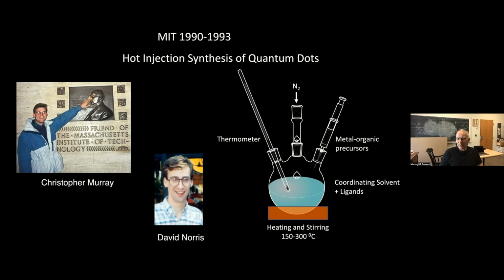And in retrospect, it's a pretty simple idea. So instead of using a water-based synthesis, since water was such a terrible thing for semiconductors, we replaced the water with organic solvents. We got rid of air because oxygen also was a terrible thing. So everything was done air-free under nitrogen with organic solvents. We used what are called organometallic precursors to bring in the metal atoms that make up the semiconductors, metal organic precursors that are under nitrogen, that are stable at room temperature. And the idea was an old idea to do nucleation and growth, but at the nanoscale.